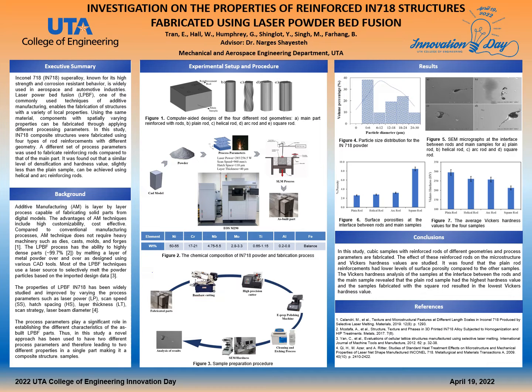Moreover, it is clear that the sample fabricated with the square rod had the highest porosity level, which can be attributed to the higher stress concentration arising from the sharp angles existing in the geometry of the square rods. According to the hardness results, the sample fabricated with plain rods resulted in higher Vickers hardness at the interface. The samples fabricated with helical rods and arc rods had average Vickers hardness values. However, the sample fabricated with the square rod yielded the lowest hardness value. This can be attributed to the highest level of surface porosity found for this sample.